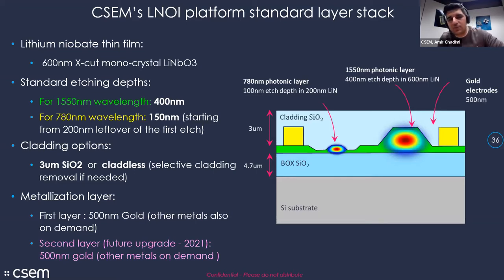Normally we take the 600 nanometers and etch 400 nanometers down to form this first layer, which we call the 1550 photonic layer. This thickness, when we simulated, is very optimized for 1550 light, and for a very good reason we don't etch it all the way through, so we leave 200 nanometers. Then your students came to us and said they were interested in doing PICs at 780. Once they simulated, they realized the optimum thickness for 780 is 200 nanometers. I said, we have 200 nanometers, we don't need a new wafer. Let's repattern this leftover 200 nanometers and etch another 100 nanometers to do PICs. So now we have these two layers.